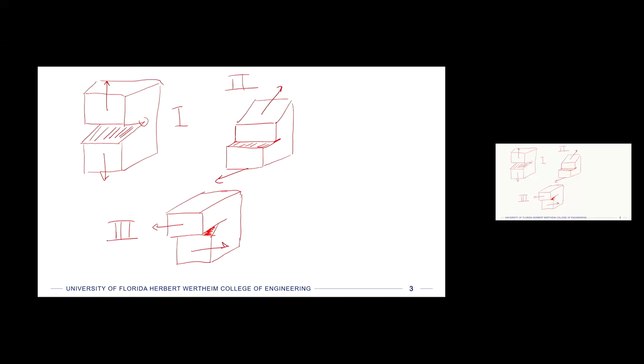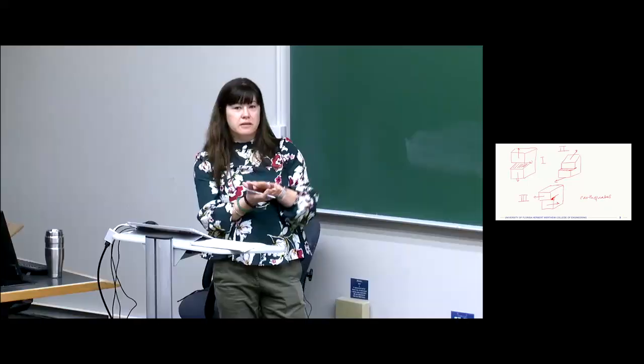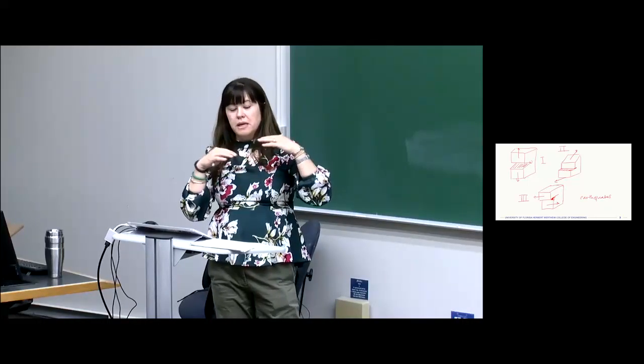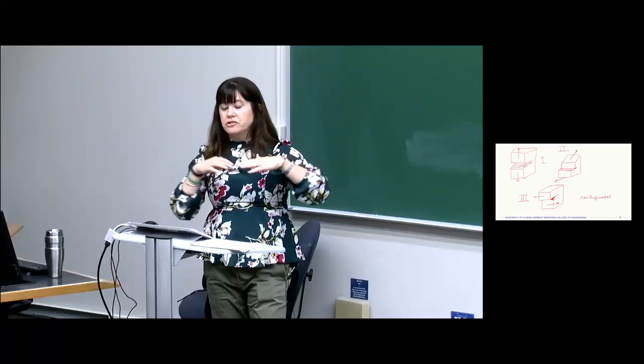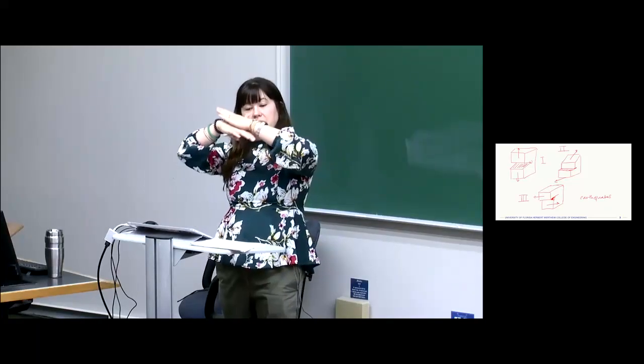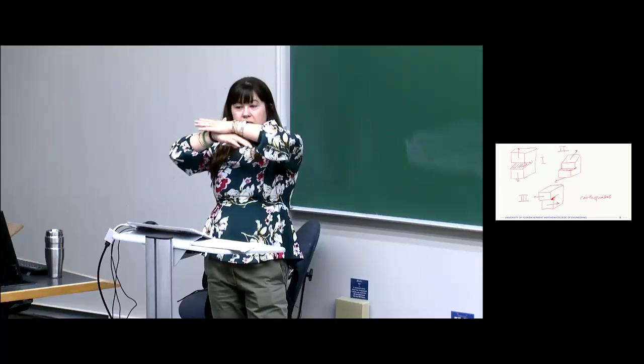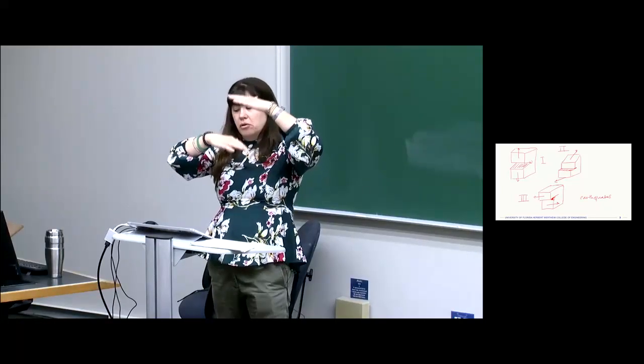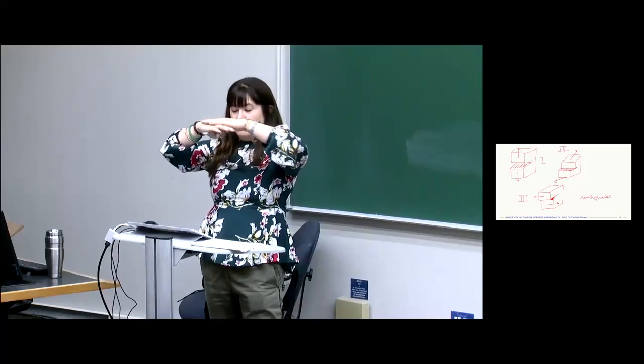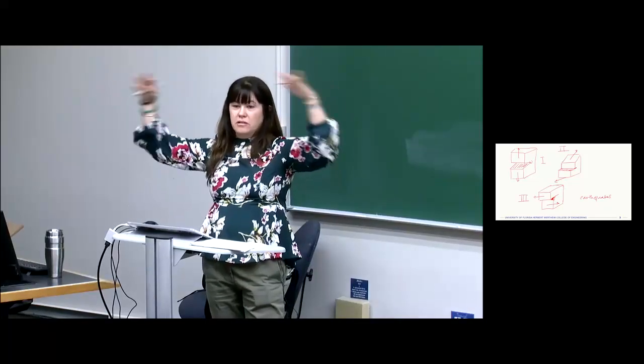We're going to look mostly at mode 1 because I said it's kind of this quintessential, most severe crack opening. But you can think of situations where these other types of modes exist. The one that I think of most commonly that has mixed mode fracture is earthquakes. So when the tectonic plates move, right, there can be all kinds of different pressures and stresses that build up to cause them to slip, and then they slip against each other, and they can slip sideways. You don't really have a lot of mode 1. It's usually mode 2 and mode 3, but you can do the stair steps, or you can have twisting, and then the way that manifests at the Earth's surface can be different ways.